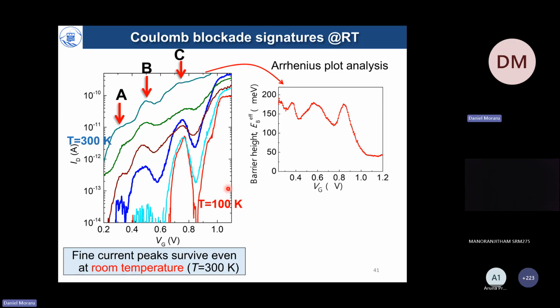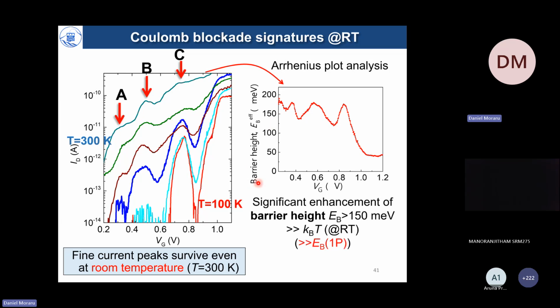Okay, so from an Arrhenius plot analysis, we can extract the barrier height. The effective barrier height is relatively large, 150 millielectron volts, and that is significantly larger than the kBT at room temperature, than the barrier height of a single dopant. So everything is fine. These oscillations are due to so-called Coulomb blockade of activated conduction.